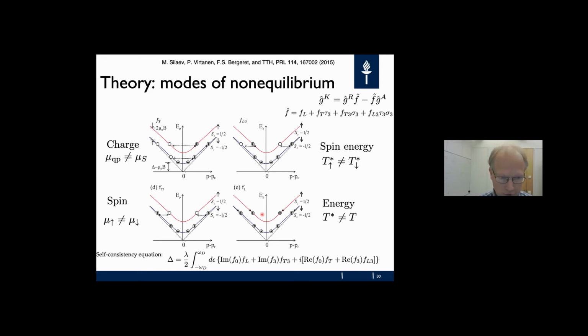You can also couple this to the self-consistency equation, and you get corrections to delta. So FL is the energy mode, and this is hyperbolic tangent in equilibrium, which is what you get in the equilibrium part. But then you also get non-equilibrium corrections due to these non-equilibrium modes and the presence of spin triplet pairing.